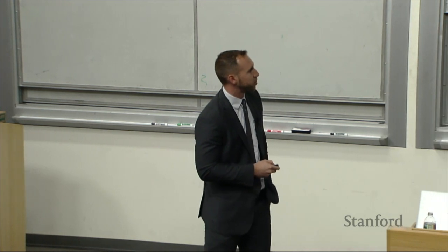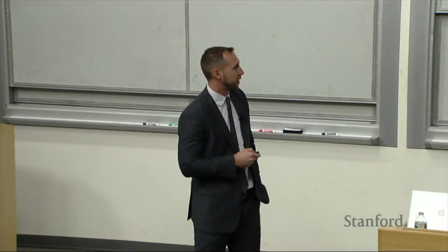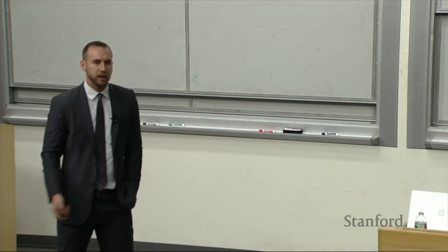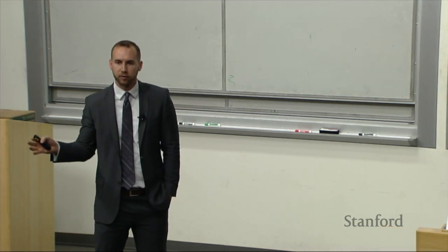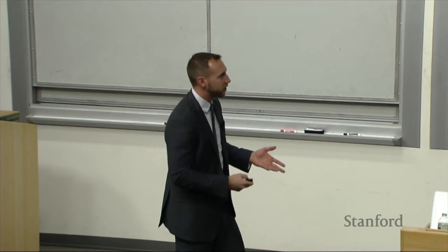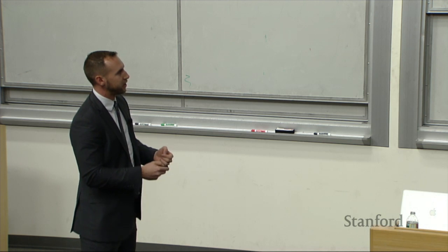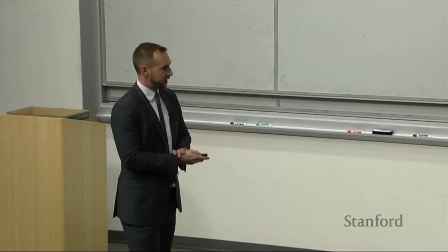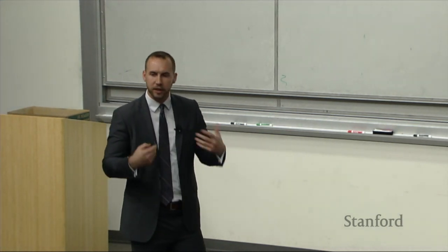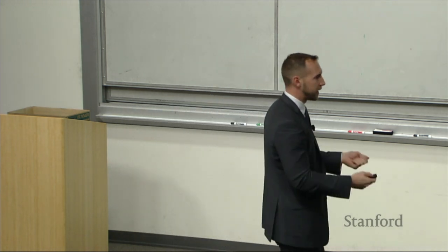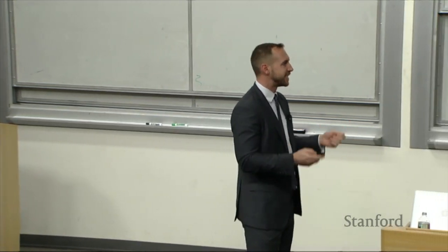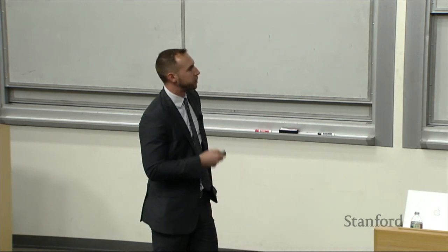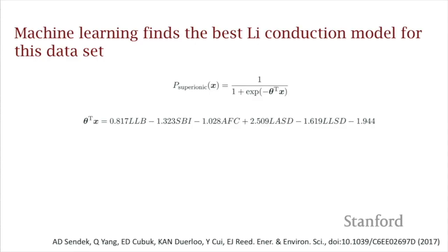I know there's a lot of lines in this plot, but I would draw your attention to this dotted red line. This was a control where we replaced all that feature data with 20 columns of random noise generated by a random number generator, and we redid this fitting process. You can see that the error is about 3 times lower when we're using our real features than when we're using noise. That is a confidence builder that we're building this model on real information, and we're really capturing something statistically significant here. Our hope is that this optimal model will give us an accurate guess about 90% of the time.